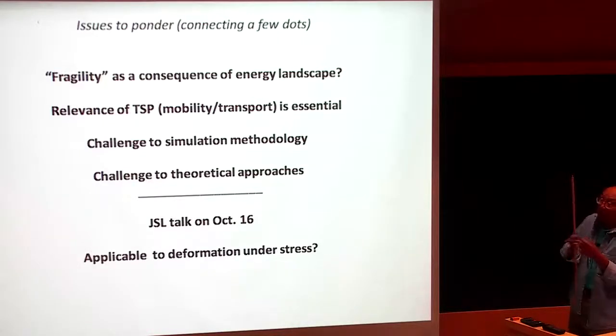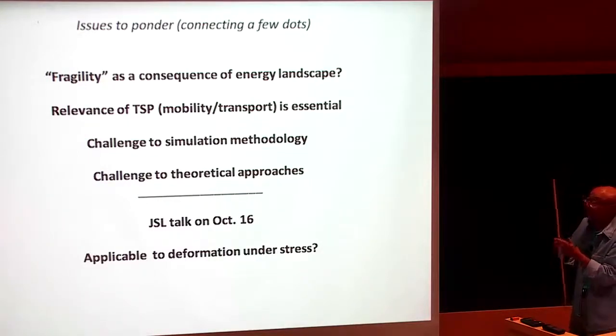So, it's not at zero temperature, it's finite temperature. So this problem of the glass transition, the viscosity or transition temperature, to me is a thermal activation problem. There's no stress, supposedly, because we relax everything, constant stress, zero stress.